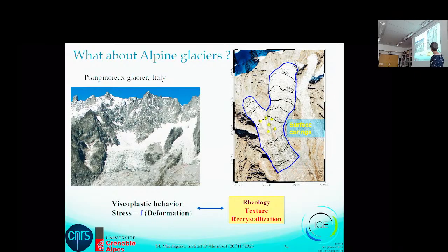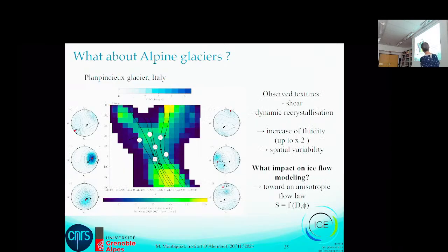steep slopes here at the side, and therefore the ice is what we call at a shear margin, and it's not only submitted to the horizontal shear, but it's also submitted to some lateral shear because of the ice being blocked by the cliffs that are there. And the good thing is that, once again, here the texture is very coherent with some lateral shearing here. So we were quite happy about that.